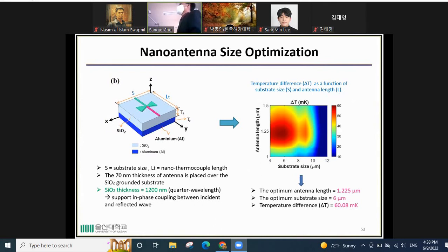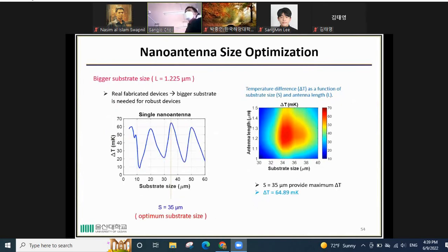So this is the temperature difference as a function of the substrate size and the antenna length. From this, we can see that a temperature difference of 60 millikelvin is achieved when the antenna length is 1.225 micrometer and the optimum substrate size is 6 micrometer. But in a real fabrication device, a bigger substrate size is needed for the strong devices. So that's why we increase the substrate size with a fixed antenna length. And this is the plot of delta T as a function of the substrate size with 1.225 micrometer antenna length. From this plot, you can see that 35 micrometer substrate size provides the optimum temperature difference.